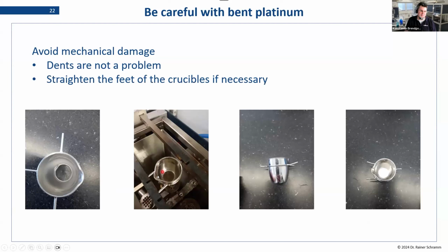There is this effect that the little pins that hold the crucible in position deform over time due to thermal and mechanical stress. So with time, they look like this. They usually bend downwards. So what you want to do is straighten them out every now and then. If you see a crucible that is a bit bent, just take some pliers, bend it carefully back into a straight position, and you're fine. Usually the ring can handle the stress. You don't want to put them in your machine like this, because there is the danger that they simply drop out, and then you have a big mess in your fusion equipment. So you definitely want to avoid that.